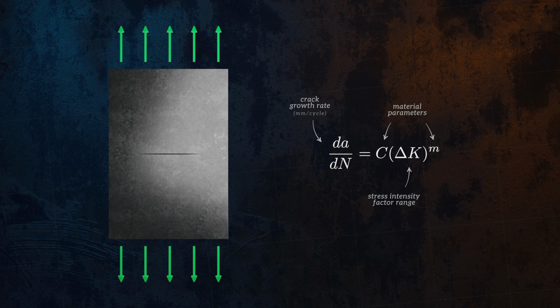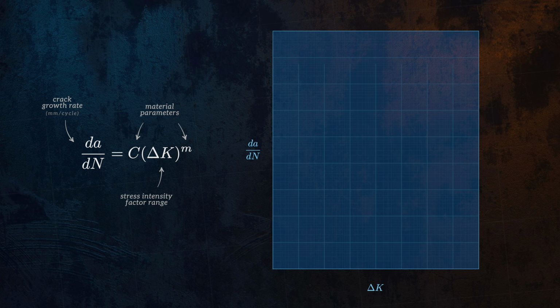On a log-log graph of growth rate against stress intensity factor range, Paris's law appears as a straight line. Because delta K is raised to the power m, small increases in delta K produce disproportionately large increases in crack growth rate. For m equal to 3, doubling delta K increases the crack growth rate by a factor of 8.